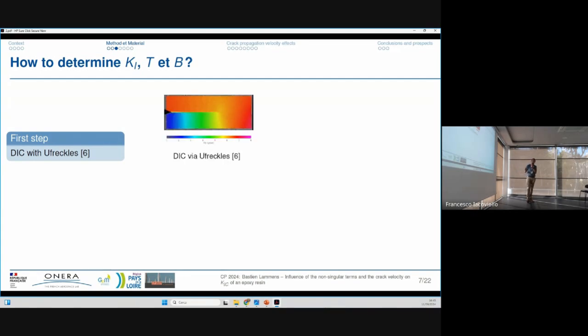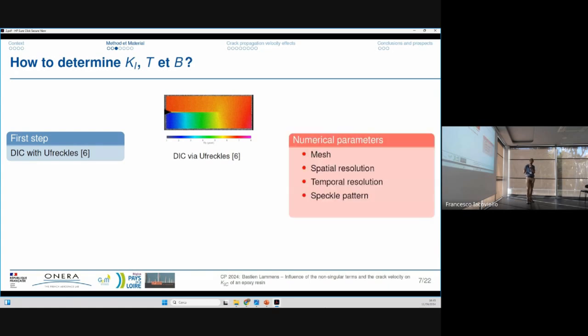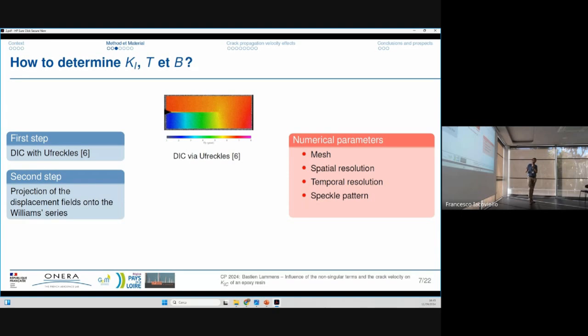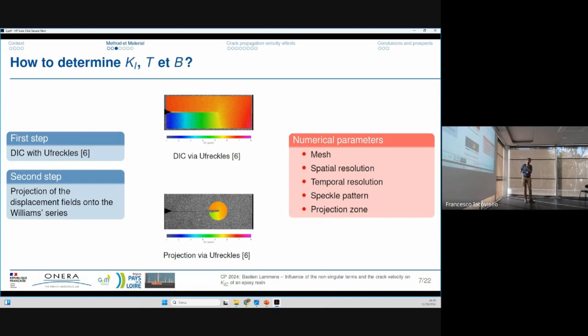So the question is how to determine these three terms. We developed a method based on digital image correlation with Ufreckles software. We have an example of digital image correlation here. With numerical parameters, mesh, spatial resolution, temporal resolution, speckle pattern, we need to be careful with these parameters. And the second step is the projection of this displacement field onto the Williams series. We have an example of the projection here. And we have to be careful with the projection zone, especially the minimum radius and the maximum radius.